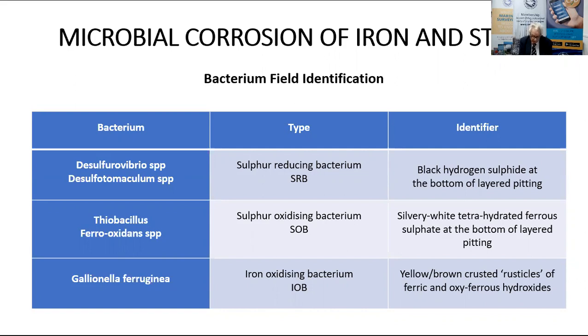If MIC is discovered, it used to be practice to thoroughly clean the hull with high pressure fresh water, allow the hull to dry off, and then coat it with a good quality biocide, sodium hypochlorite or common bleach. Wash off again, afterwards carefully recoat with a compatible paint. However, because of environmental concern, it has been considered better to use a 70% percentage of isopropyl alcohol. That's the spirit stuff that when you go into a hospital, you're asked to wash your hands with before you go into the ward.